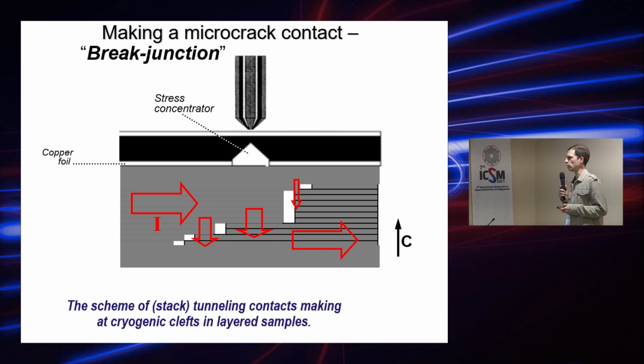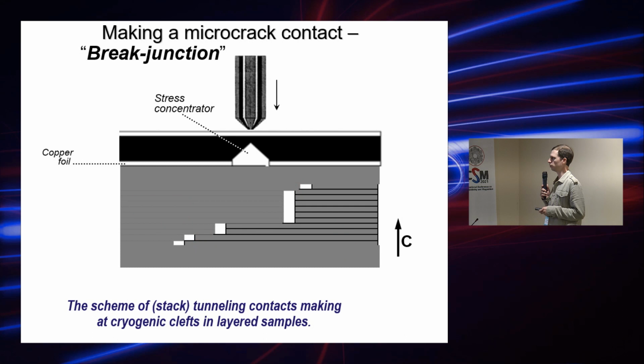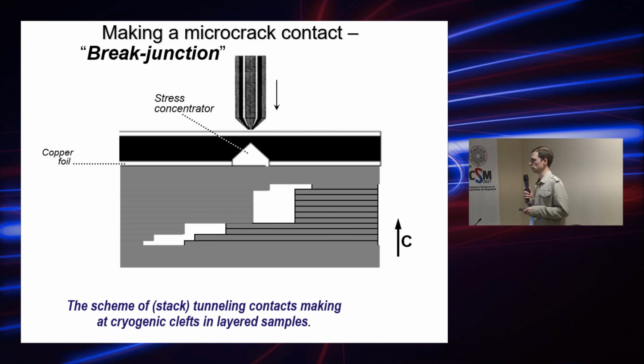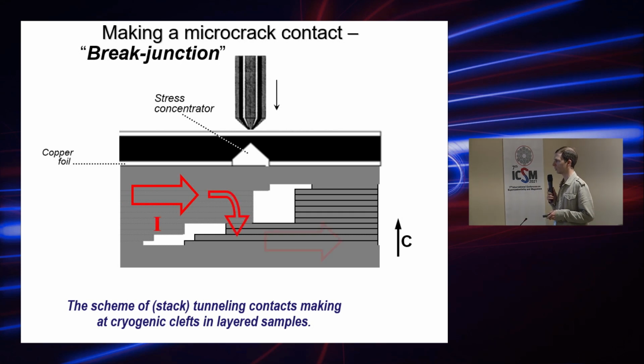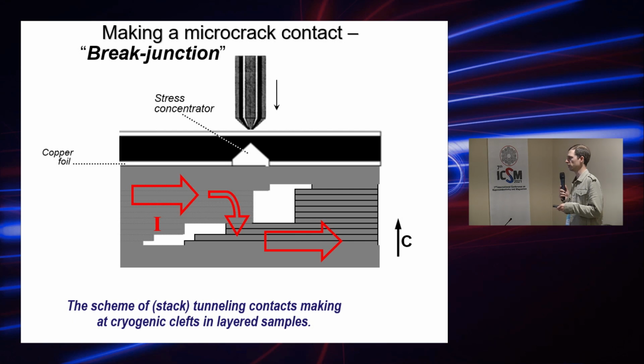But nearly every time you have a possibility to apply the stress so that the curvature of this experimental table produces only a single contact to one of the terraces. And of course it's simple to understand that the height of any terrace is some natural number of the elementary layers of the sample. But thus we are sure that the current injection goes directly in the C direction.